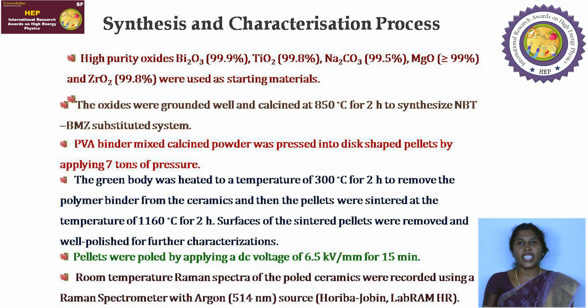The synthesis and characterization process. For the synthesis of NBT BMZ ceramics, we used highly purified oxides and carbonates. The starting materials which are used are bismuth oxide, titanium oxide, magnesium oxide, zirconium oxide and sodium carbonate. These powders are taken in the stoichiometric ratio and ground well and calcined at 850 degrees centigrade for 2 hours. Then the calcined powder is mixed with PVA binder,